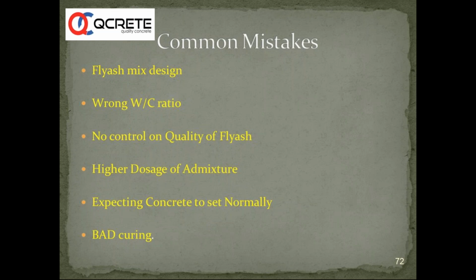If you are able to significantly reduce the water cement ratio in the 320 kg OPC plus fly ash mix, then you can hope to get a better strength in terms of OPC fly ash mix. So this particular thing you need to remember actually, as we already know that when we are using about 25% of fly ash, it gives a water reduction of 8%. So by using a PC based admixture, you can still reduce the water cement ratio further down when you are comparing at the same cementitious content. And we should always reduce the water cement ratio as much as possible when we are shifting from OPC mix to OPC PFA mix. So that is the most important point actually.